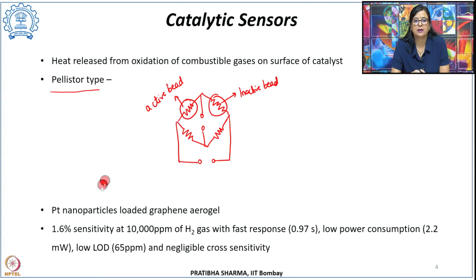Now, in this case, different materials have been considered for the catalytic sensor, like the platinum nanoparticles loaded graphene aerogel. They have been studied and have shown good sensitivity, 1.6% at 10,000 ppm of hydrogen gas. Even the response time has been very fast, 0.97 seconds. They require very low power, so low power consumption, 2.2 milliwatt, with a lower limit of detection of even 65 ppm, and they have a negligible cross sensitivity. So, this is the Pellistor type of catalytic sensor.